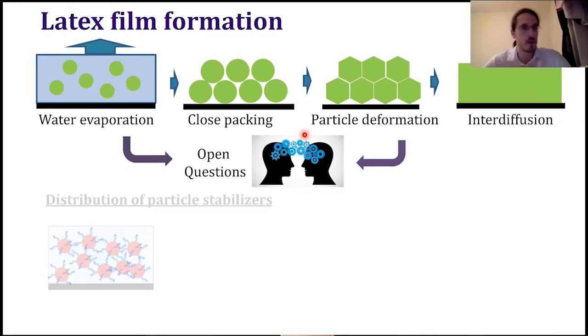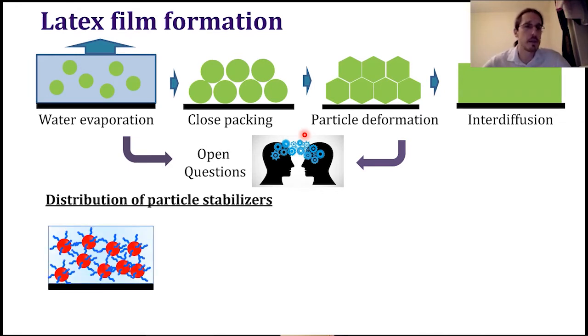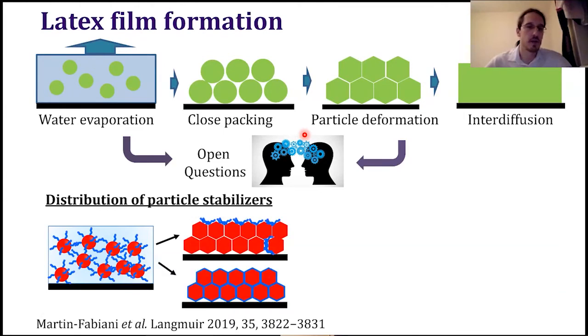For example, there is one which I won't talk about here: for all these particles to be dispersed in water, they need to be stabilized by hydrophilic substances such as surfactants, etc. One of the main challenges is to know what happens during film drying with those very hydrophilic substances, because they might hinder the performance of the coating. Do they go to the top surface, or do they just accumulate in the boundaries between particles? I left you a reference there, where we did a neutron scattering study on where these hydrophilic substances go.